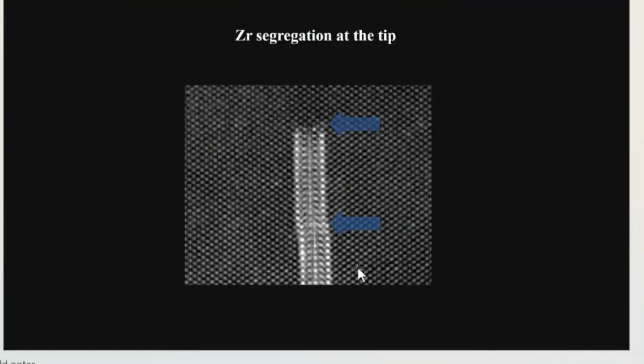plate growth stopped. And then a new plate nucleated on the leading growth edge. This is well known in the precipitation literature as sympathetic nucleation. So what is happening is that plate growth stopped for some reason, but the driving force for the precipitation is still high. So a new plate nucleates at the tip. And that is how the growth proceeds.